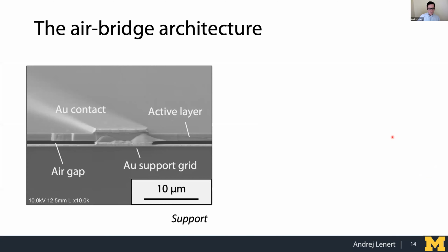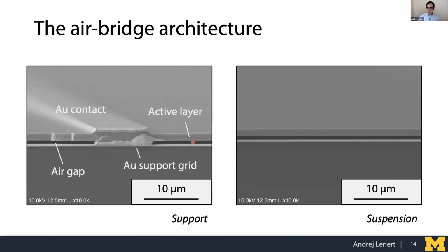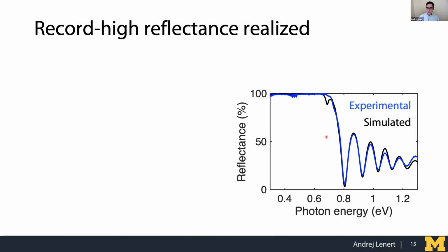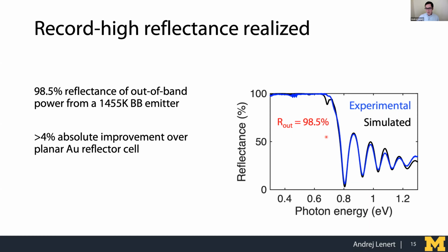This is a cross-section where we can see the active absorber layer suspended over the planar gold mirror, over this air cavity. And we can achieve spans of close to 100 microns while maintaining the 600 nanometer air gap using this simple fabrication process. And now we can realize a very high reflectance in practice that matches our simulations. So now the out-of-band reflectance is as high as 98.5%. And that high out-of-band reflectance should lead to high efficiencies.